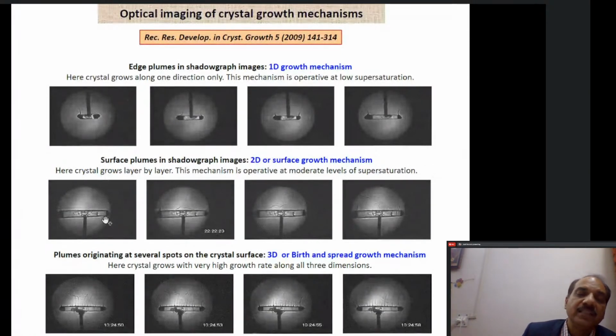Then when we increased the supersaturation, we were able to see that the plumes which were earlier emanating only from the edges of the crystal, now the entire surface of the crystal was getting involved, and the plume was rising from the entire surface of the crystal. This is what we refer to as the 2D growth mechanism. Here the crystal grows layer by layer. This mechanism is operative at moderate levels of supersaturation.